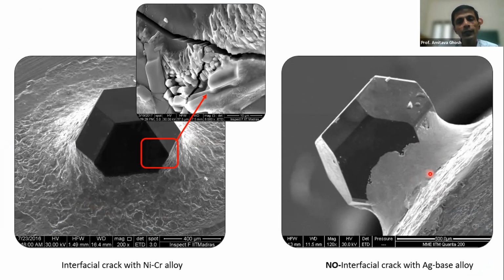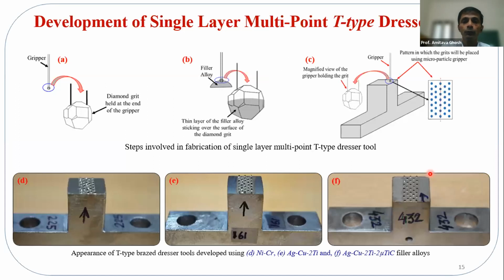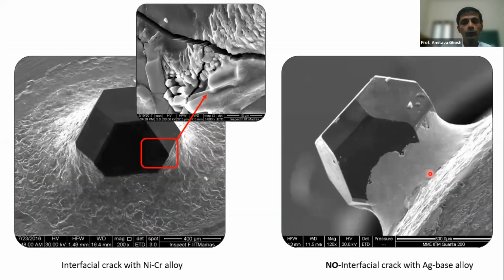Of course, here is also an active element like titanium. Titanium is also reacting with the diamond, making titanium carbide at the interface. That is also almost ceramic in nature, but still, since the silver copper matrix is much softer around it, it gives much more cushion. I'm just talking in less scientific terminology, cushioning. But finally, the main thing is basically the absorption of the residual stress is much more efficient. So we can get rid of this crack problem, and then we thought, why should we not modify this alloy a little further.